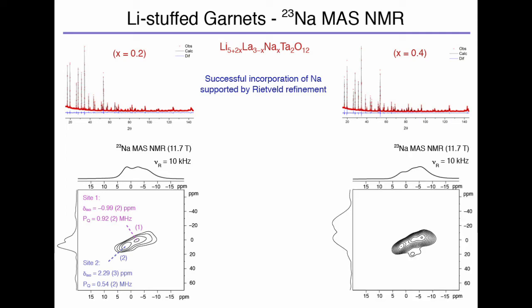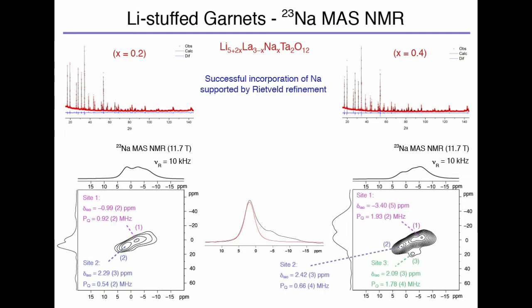We can do exactly the same for the 0.4, and you'll see, again, the spectrum on the top looks very broad, quite featureless, difficult to know how many sites. So again, we can apply these two-dimensional techniques, and when we do that, we can see a minimum of three distinct peaks, which is a bit unusual. Because why do we see more sodium sites for 0.4 relative to 0.2? So the number of sodium environments seems to vary depending on the composition. So this makes us scratch our head, where is the sodium going in this material?